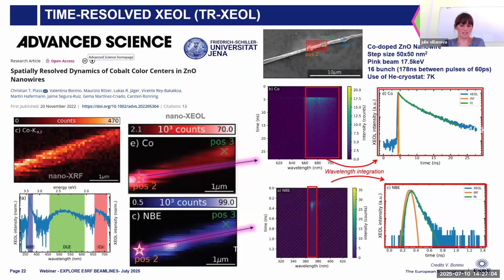And then the XEOL signal that we retrieve, I always say we, but it's the scientists performing the experiment, is composed of three different luminescent signals, which are the near band emission, the deep level emission, and the cobalt luminescence. Now, if we focus on the point where there is a high concentration of cobalt, and we record using the streak camera the decay of the XEOL signal, and we decorrelate the wavelength. So here we integrate the wavelengths that correspond to the cobalt luminescence, and here we integrate the wavelengths that correspond to the near band emission. We see that the response is completely different.